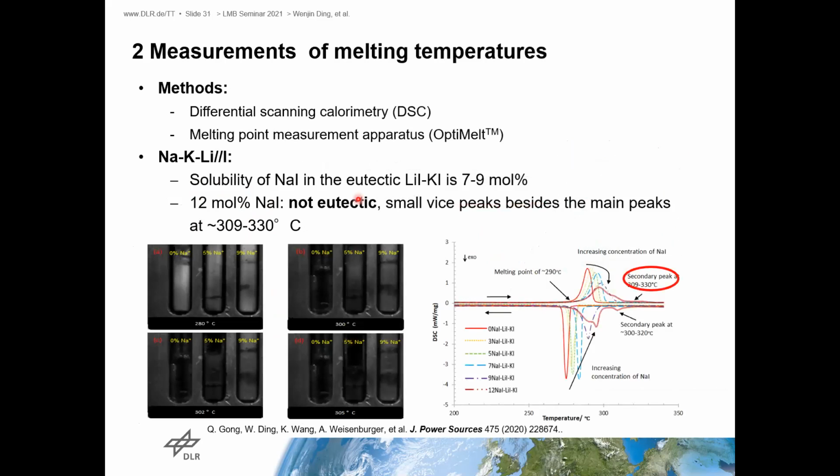After the simulation, we use DSC and a calorimeter as methods to measure the melting temperatures. The measurement found the solubility of sodium iodide is about 7 to 9 mole percent. It's lower than the simulated values.